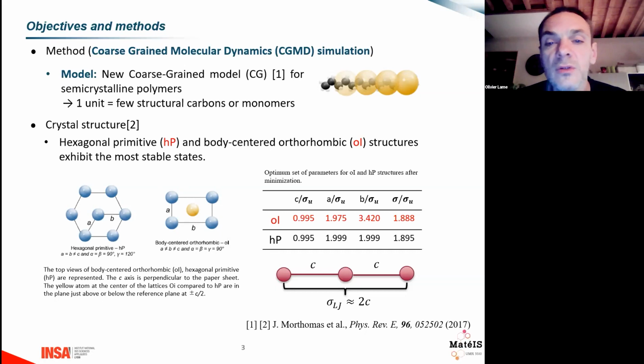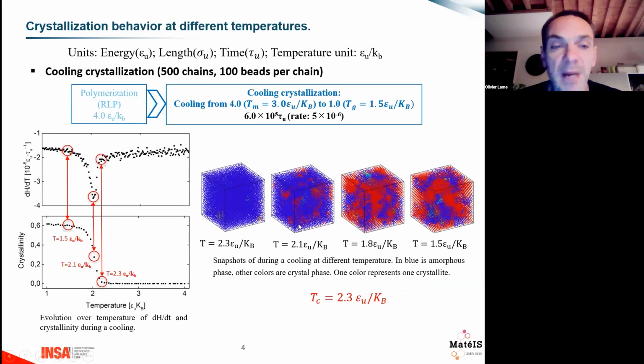Okay, so we get this kind of microstructure. You have here the variation of the enthalpy, which decreases a lot when we crystallize. Here we see the maximum of crystallization. And then we go from a high temperature, here the units are Lennard-Jones units, to a low temperature, and we see the crystallinity being created and increasing along with the decrease of the temperature.